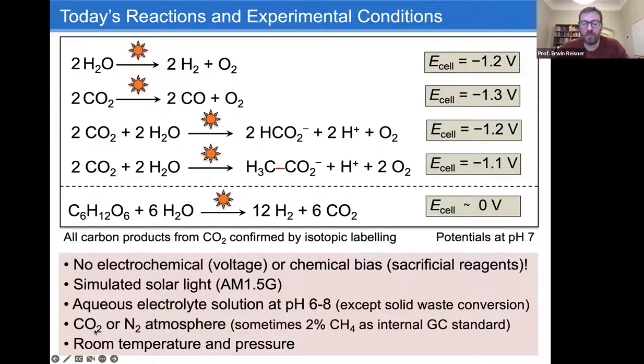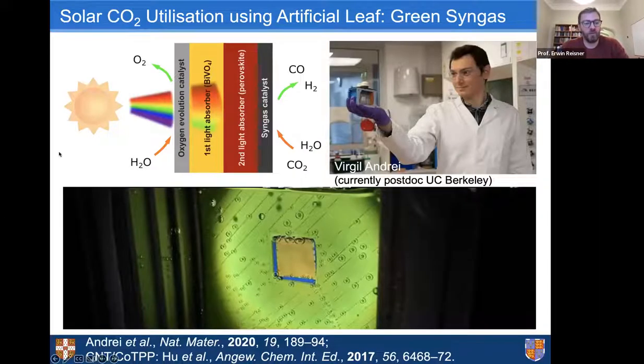And everything is done at room temperature and pressure. So it's also not a high temperature process or high pressure. It's all room temperature and pressure. So ambient conditions, except that we usually avoid oxygen in the product. So it's anaerobic at the start of the reaction. Okay, so to delve straight in, the first system I'd like to show was assembled here by Virgil Andrei. And this is already one of these artificial leaves for CO2 reduction.